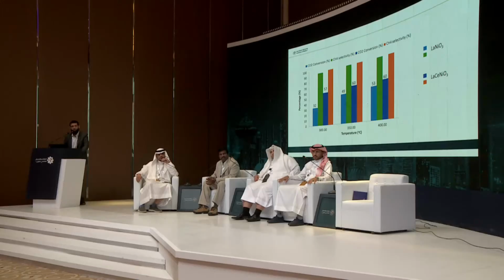at 300 degrees centigrade. So when the temperature is increased, the CH4 selectivity is reduced a little bit, but the CO selectivity is increased. So we need to have higher CH4 selectivity and higher CO2 conversion at as low a temperature as possible. So in this case, the addition of ceria gave better activity, and it gave us better CO2 conversion.